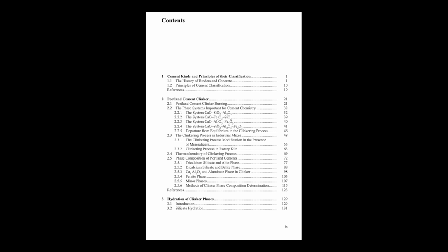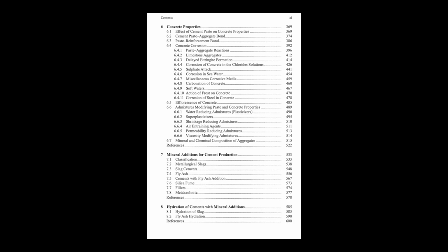The big picture. Because the properties of cement paste and concrete, especially strength, but also permeability and durability, are overwhelmingly determined by the characteristics of this CSH phase. It's the glue holding it all together. Essentially, yes. The interconnected network formed by these tiny particles creates the rigid load-bearing structure. This interconnectedness at the nanoscale is what defines it as a gel in this context. A system with strong cohesive forces making a continuous network. Exactly. Our sources even reference solubility data showing the equilibrium conditions for metastable CSH phases forming early on, particularly during tricalcium silicate hydration. Highlighting how those initial pathways dictate the final binder.